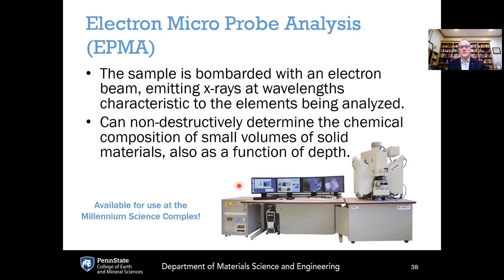Another way to measure concentration profiles is electron probe microanalysis, also called microprobe or EPMA. This is another example of bombarding the sample with some high energy particles, releasing something from the sample, and then analyzing them. The difference is really what you bombard the sample with and what the sample releases. With SIMS, we were bombarding the sample with ions. In this case, with EPMA, we are bombarding the sample with an electron beam. And what gets released are X-rays from the sample that are at wavelengths characteristic to the elements being analyzed. And then analyzing the intensity of the X-rays at different wavelengths gives us the concentration of those species.